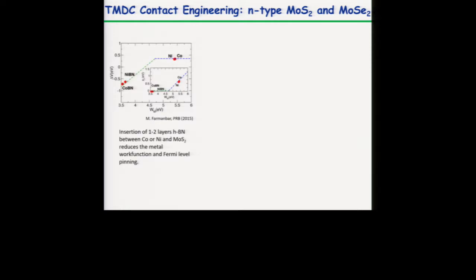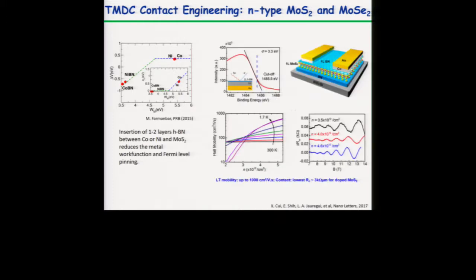What happened with N-type? All I mentioned is mostly for P-type. As I said, we are using these noble metals. We're placing the TMDC on top of the metals. What if we want to make contacts on N-type materials like MoS2 or MoSe2? In that case, there is a theory paper where they claim that if you introduce boron nitride to cobalt or nickel, the work function at the end reduces. And it's all because of the interface.